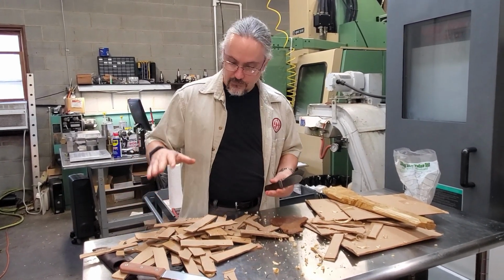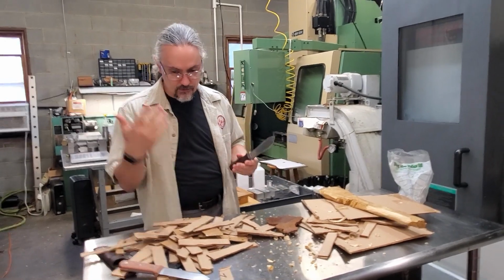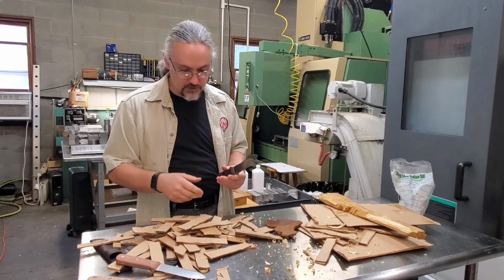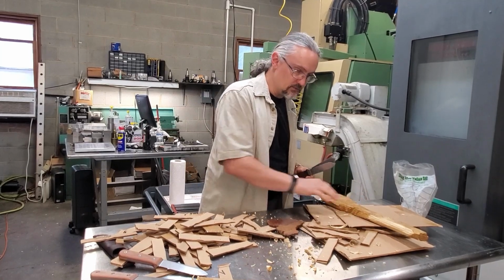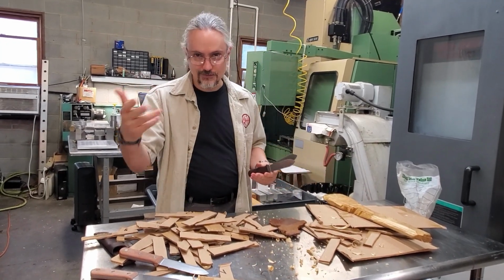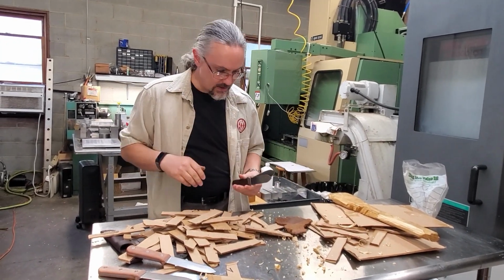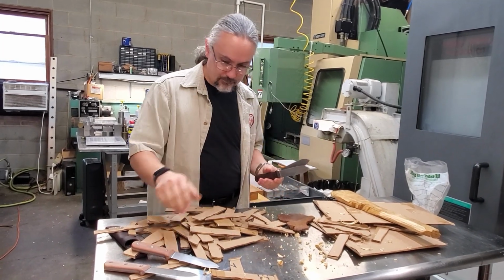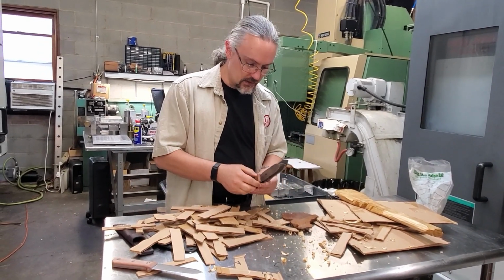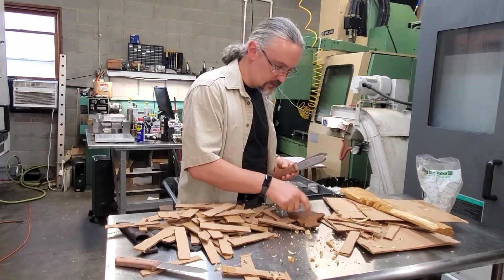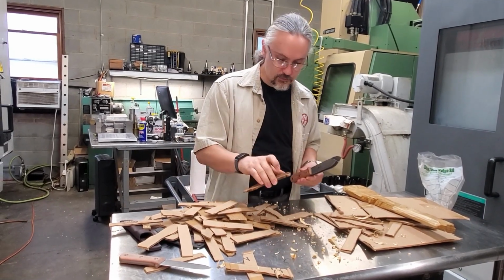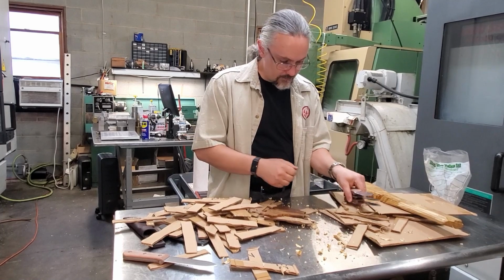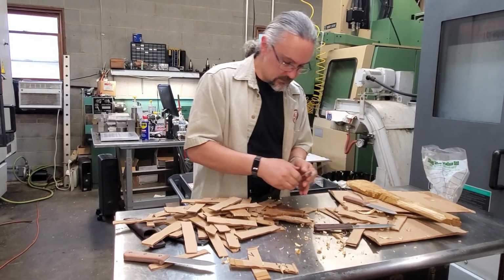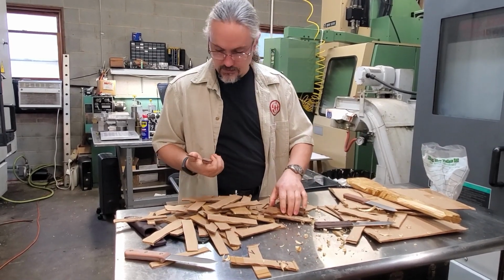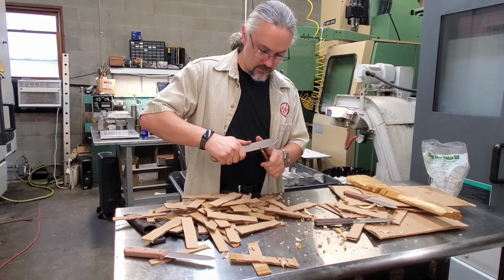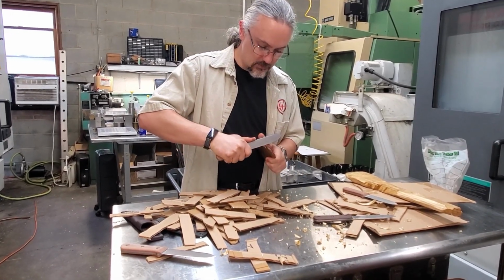So what we'll do, so I've cut some cardboard. I already know I'm going to see a little bit of wear in the simple steels. We cut some seasoned wood. This is how I do it, but I don't usually do it just talking to somebody. I'll stop and we'll look at it under magnification. So at this point, you will start to see some differences, but the Osage orange, this is a really hard piece of hardwood, and these cuts where I'm putting it in there and leveraging it out, that's where the edge damage really starts to become apparent.